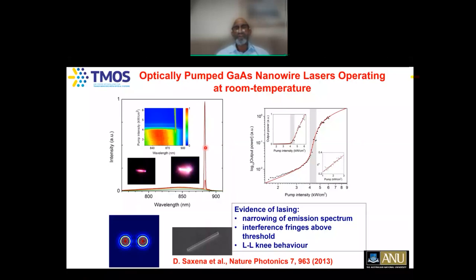You can also see the beautiful interference fringes because of the coherent light coming out of these nanowire lasers. In fact, Drew Saxena has compared these simulations with experimentally measured interference fringes, and they match very well. This is the output versus pump intensity. You can see threshold-like behavior in the log-log plot, showing spontaneous emission here, amplified spontaneous emission here, and lasing taking place here. The three requirements are threshold-like behavior, a log-log plot, and narrowing of the line width, and we were able to demonstrate all of them. This work was published about 8 years back in Nature Photonics or so, and Drew Saxena's hard work, along with other students, really paid off.